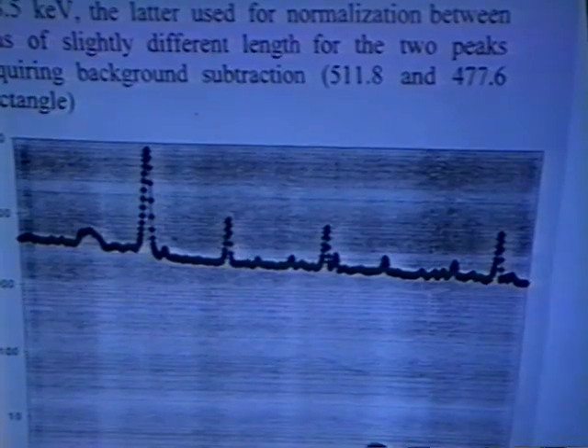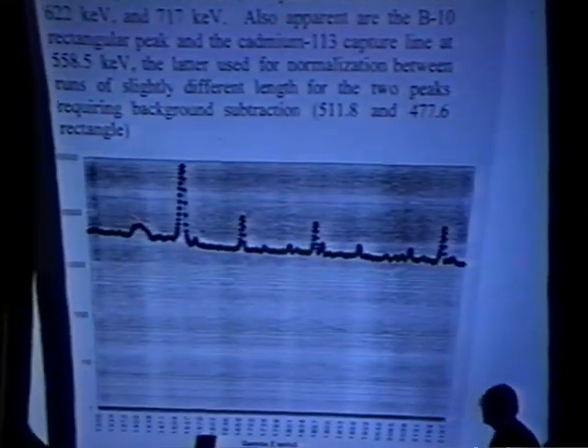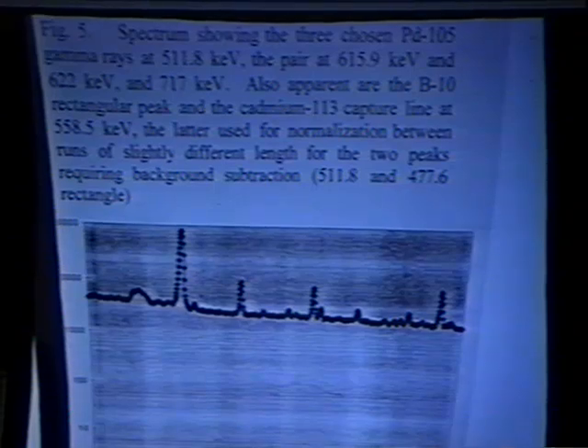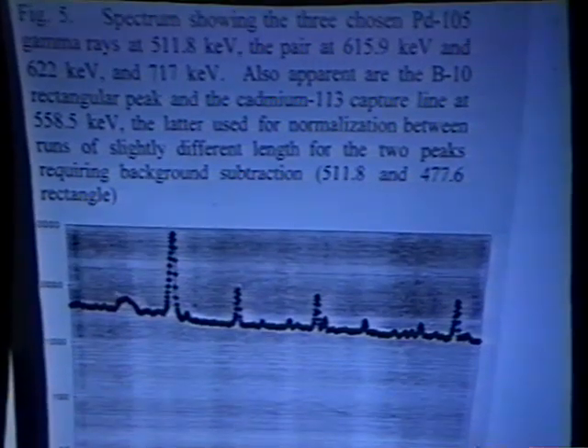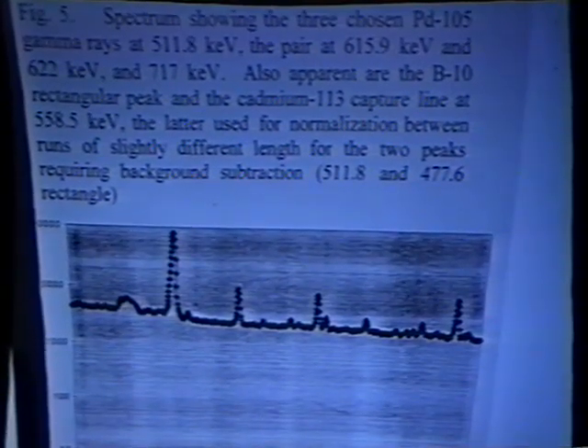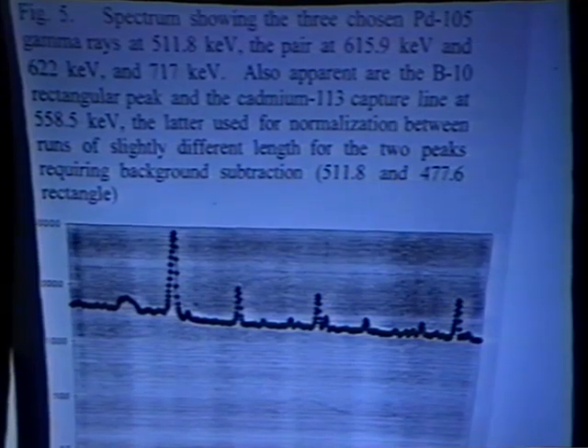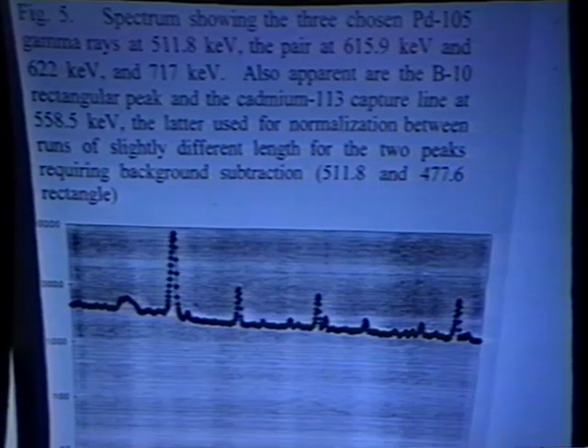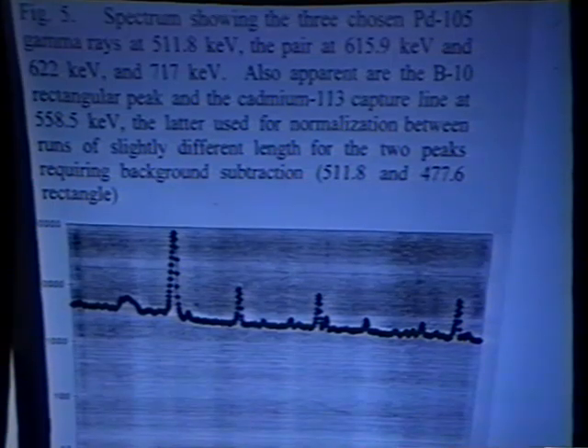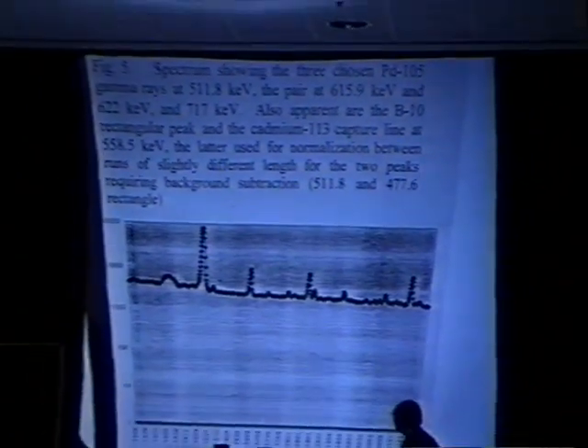Here's the spectrum of a limited region of the spectrum. Here's the B-10 rectangular peak. Boron-10 produces an n-alpha reaction, giving you lithium-7, recoiling at a very high rate. And so it gives you Doppler broadening of its otherwise sharp peak.